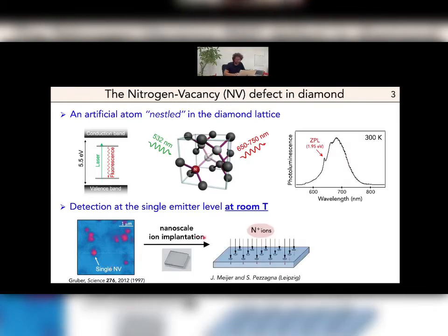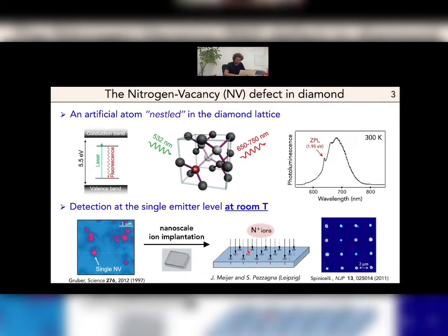It is pretty simple: you just shoot nitrogen ions inside diamond to create NV defects. And this works, and this is a typical result that you can get here, where you can create arrays of single NV defects through ion implantation.